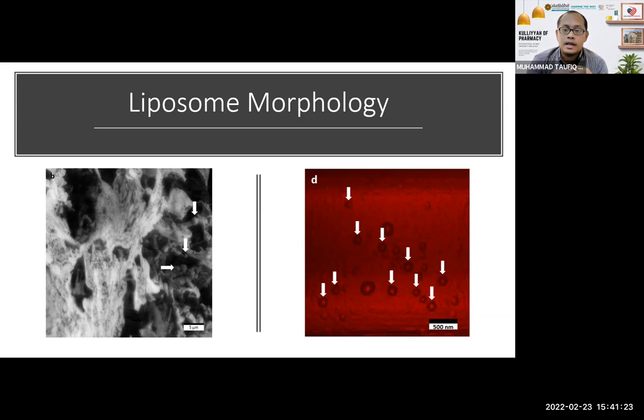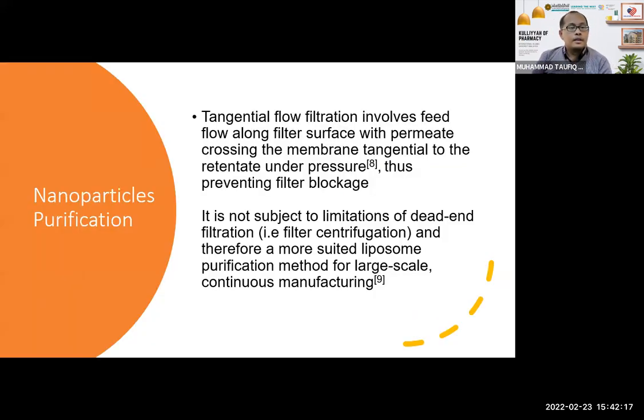But then again, we do what we can with what we have. You cannot really count and size every single one of them in situ, because you have thousands and thousands of liposomes at once. But we do find some variations between these types of measurement in terms of sizing. For example, if you look at the SEM there, actually some of the liposomes are covered by trehalose. The trehalose forms a continuous matrix, like bridges between these liposomes. So if we say that that is the actual size of the liposomes, you might not be correct, because there is some trehalose covering the liposome itself. So what you can say for sure is that it looks like that, and that's all there is to it.